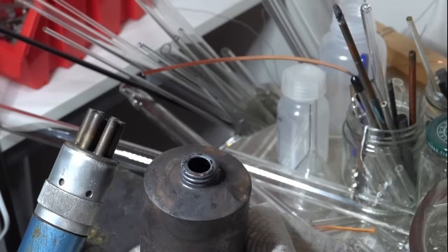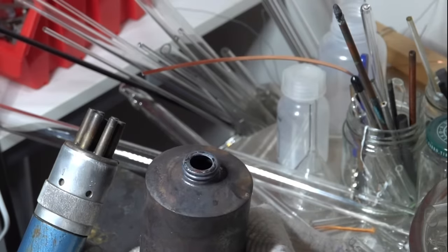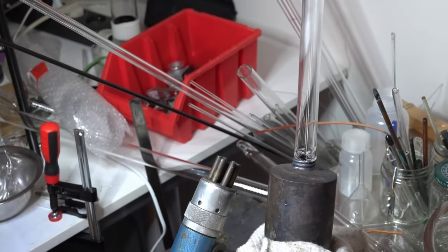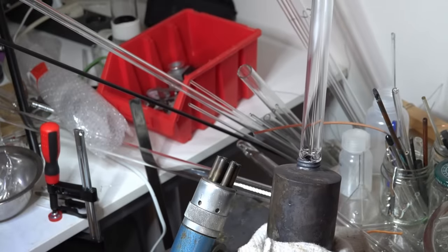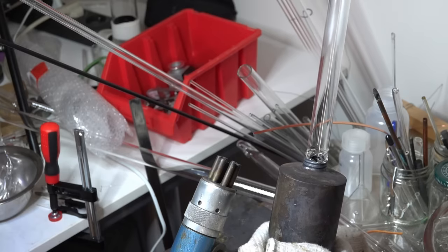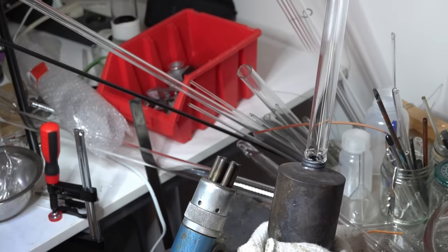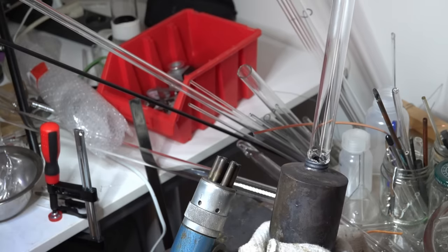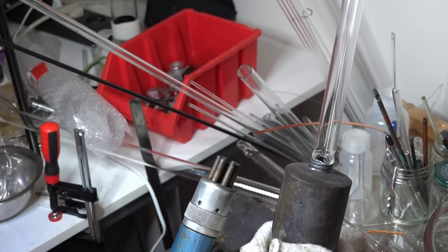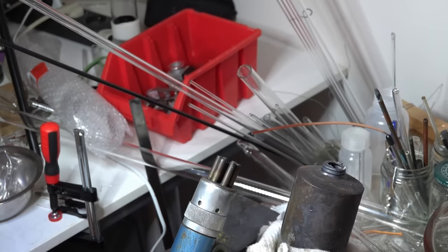And this is basically what you would have had with the Titan sub. When it was mated together, both sides had exactly the same dimensions, and so everything was hunky-dory. However, once it got down to its deepest point, the diameter of the carbon fiber wants to be about 1% smaller. It wants to shrink by about 1 centimeter in diameter. Meanwhile, the titanium doesn't want to change its shape at all.